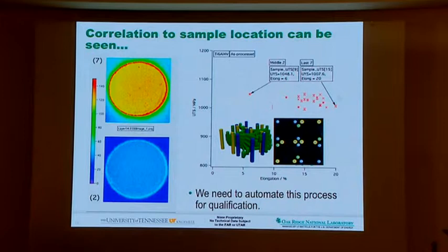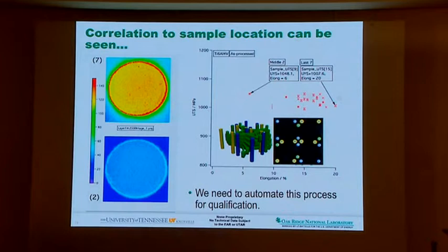So let's look at this hypothesis we have. We took the tensile samples and did room temperature tensile testing. What you see on the diagram is the ultimate tensile strength, where you go beyond the yield point and it fractures; that is the ultimate tensile strength. Then we can look at the elongation for the same samples. The sample which was cold all the time had a lower elongation, whereas number 7 has very good strength and also very good elongation. That clearly shows the hypothesis that tensile tests show similar properties is not good, because each and every tensile sample goes through a different thermal signature.